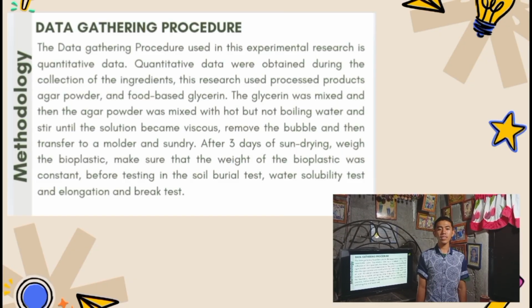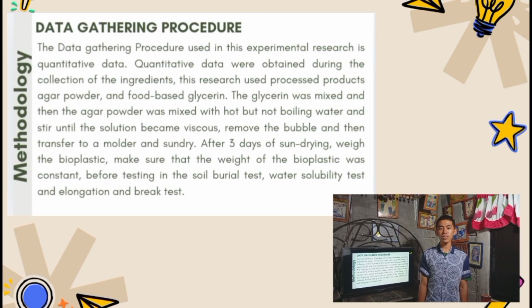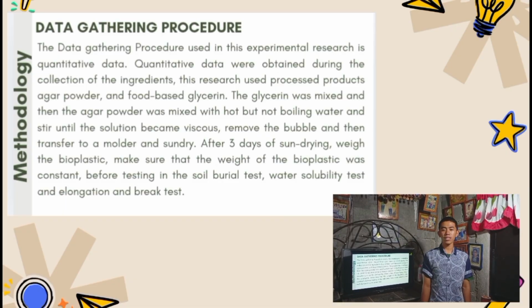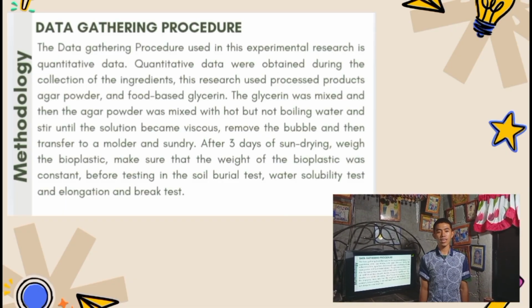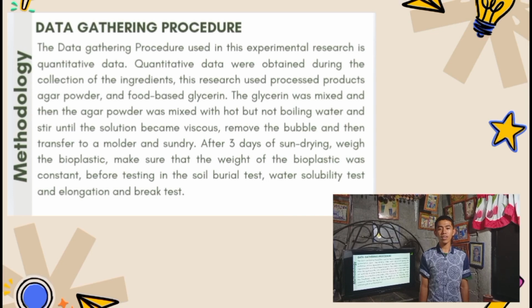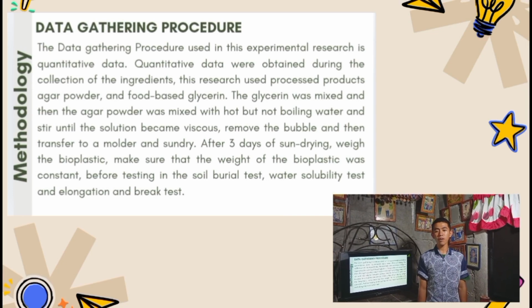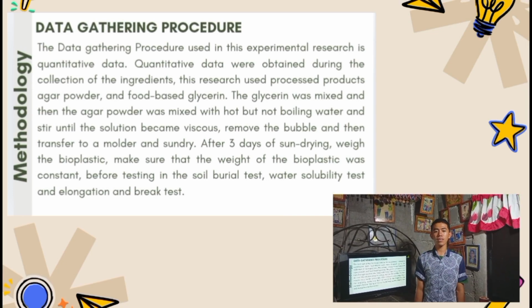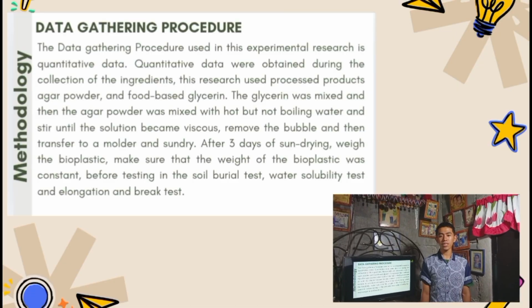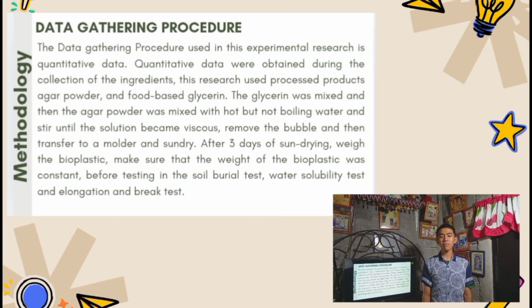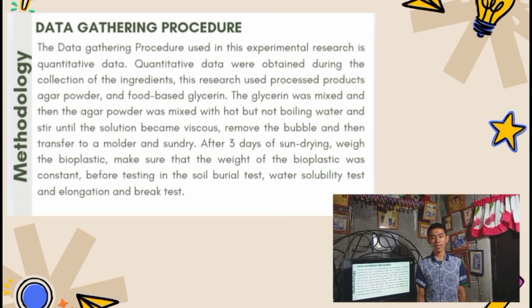In the water solubility test, the bioplastic is submerged in 800 ml of water for 24 hours and sun-dried again to reach a constant weight. The purpose of this is to evaluate the performance of agar-based bioplastic as a viable eco-friendly alternative to traditional petroleum-based plastic.